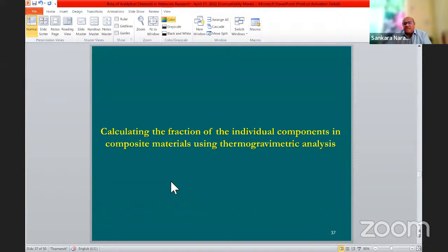I'm going to talk about thermogravimetric analysis. We recently prepared a composite material, for example, of hydroxyapatite and graphitic carbon nitride. Graphitic carbon nitride is a well-known visible light photocatalyst, and hydroxyapatite is a very good biomaterial. We prepared a composite of hydroxyapatite and GCN, and after preparing it, we wanted to analyze how much HAP and how much GCN is there, because it's a single powder. For that, we used thermogravimetric analysis.